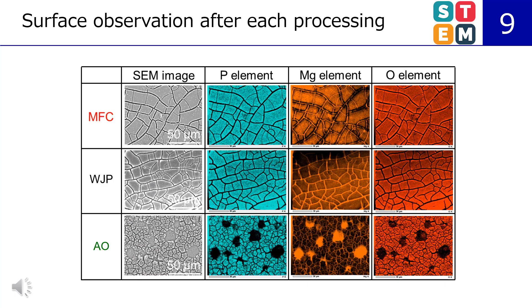These results of SEM observations of each treated surface are shown. Cracks exist on the surface treated with MFC or WJP and a film is formed. However, in anodizing, there are areas where the film has been peeled off in addition to surface cracks. It is confirmed that MFC and WJP are superior to conventional methods in film formation.